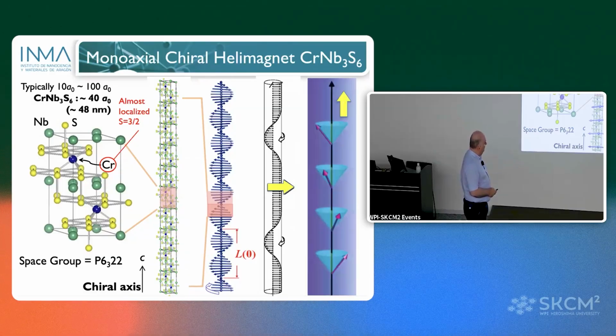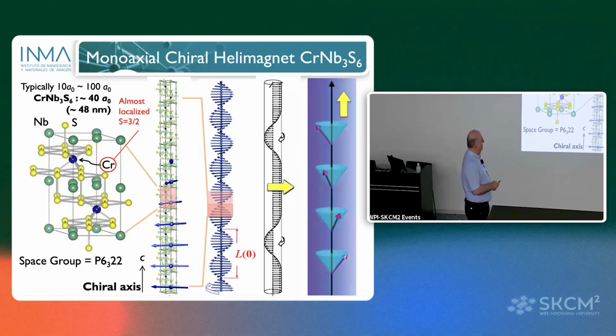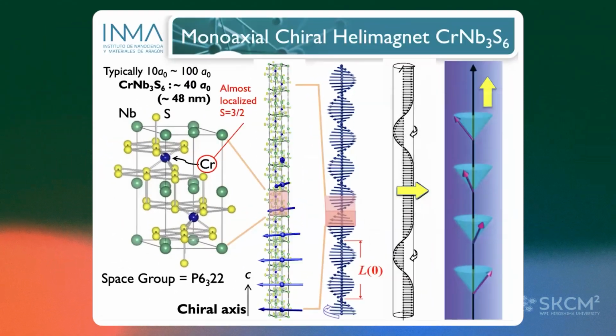However, if you apply the magnetic field parallel to the chiral axis, you are closing this angle, you are closing the cone, and you will end up also with a ferromagnetic system pointing along the chiral axis. In this case, it is an instability, and in this case it is a nucleation phase transition.